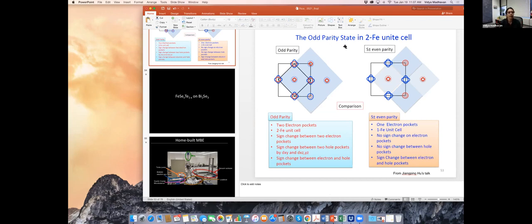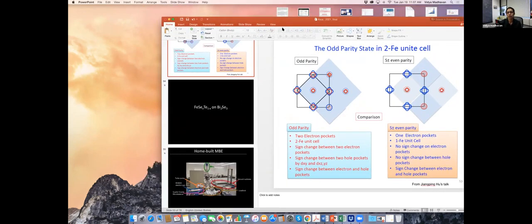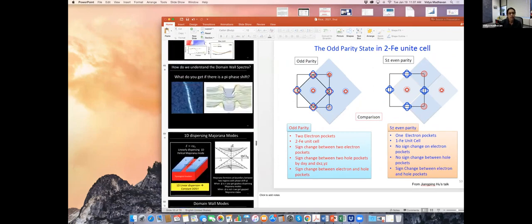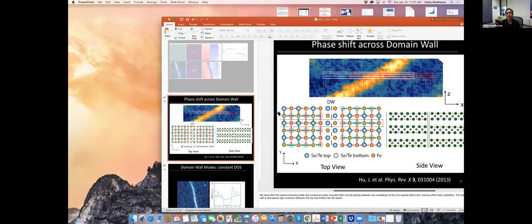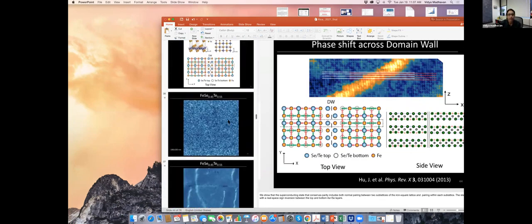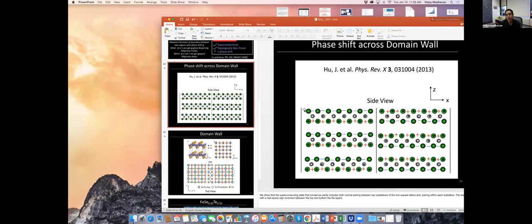Not just FeSe, depending upon the circumstances. He's saying many of the pnictide compounds could be in this particular state, where if you do realize this kind of effective odd parity superconductor, then the proposal would be that not only do you have a sign change in the order parameter between the hole and the electron pockets, as shown here on the right, but you also have a sign change between the two hole pockets themselves. And this is the same idea where the top layer and the bottom layer also show, in real space, a phase shift. So those two things go hand in hand.